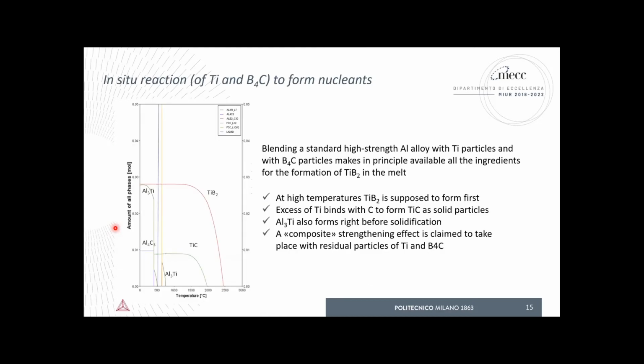Again, just to understand how the process works, this is a plot summarizing the stability of the phases under equilibrium, in this case calculated for the standard alloy I was talking about in the last slide, containing originally titanium and boron carbide in the composition. Okay, it's equilibrium. It's not a solidification simulation, but I think it's clear enough. It's good enough for us to understand the stability of the different phases during cooling down from very high temperature, exactly under the laser beam, to lower temperatures.